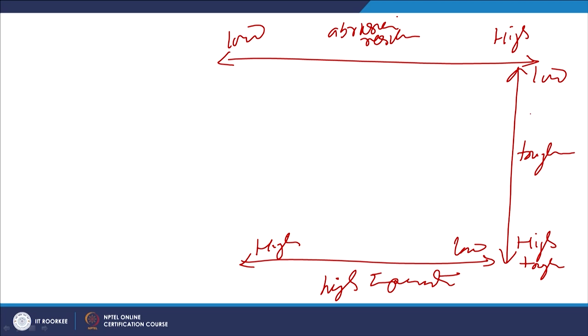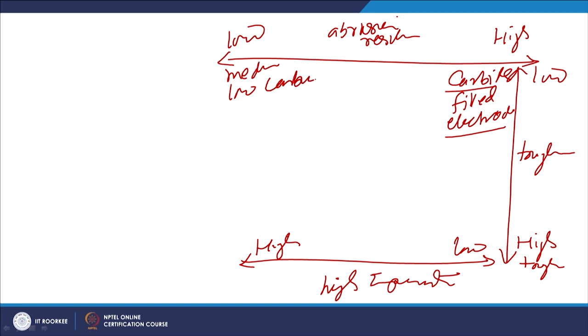So this kind of situation is there when the carbides like tungsten carbide, chromium carbide filled electrodes are used. So they offer very good abrasion resistance, but they offer the low toughness. On the other hand, here we can use the low abrasion resistance materials, like medium and low carbon steels, high carbon steels.